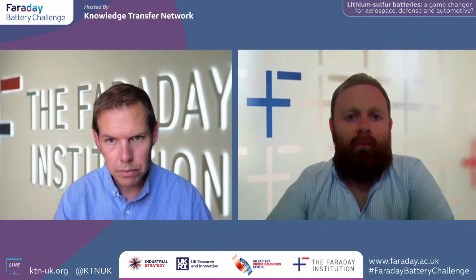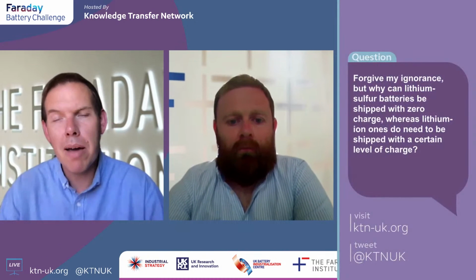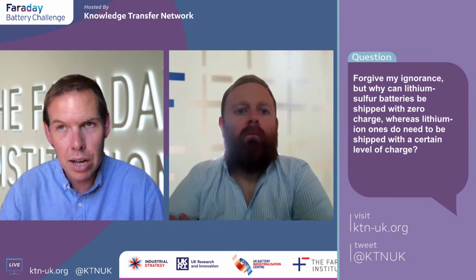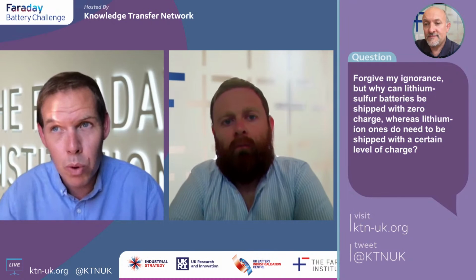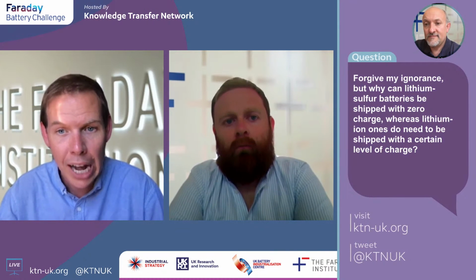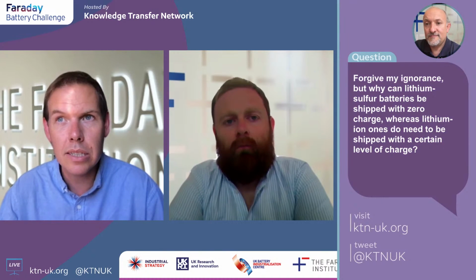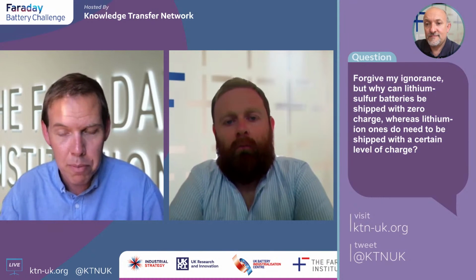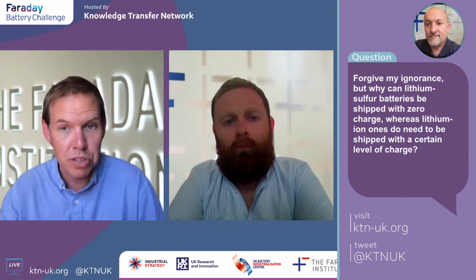Okay, you kind of hinted at this one, but the question just comes in a bit more detail: don't give us the full detail, but why can't lithium-ion batteries be shipped at zero charge, and therefore why can lithium-sulfur? What's the key difference? Well, one challenge with lithium-ion batteries is that if you discharge them to 0 volts, you can get a reaction between the electrode and the current collectors, and that doesn't happen in lithium-sulfur batteries because of the different materials and current collectors involved.